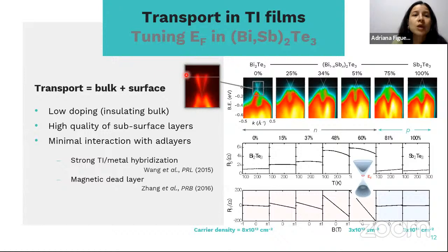So it has also been established how to tune the location of the Fermi energy within the gap of these materials, for example for this alloy, which we call BST, bismuth antimony telluride. We've seen that the position of the Fermi energy depends on the concentration of antimony in the material. And this is relevant because with that control, we are able to suppress the contribution of bulk carriers to the electronic transport. What does it mean?